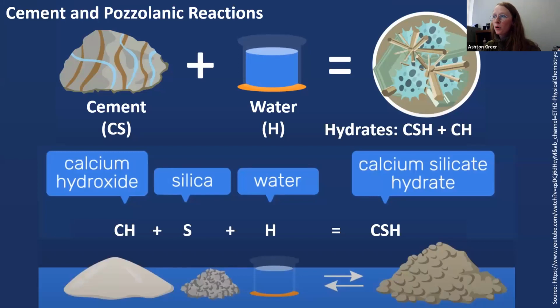So hydraulic cements like Portland cement become adhesive through a chemical reaction between the dry ingredients and water. Hydraulic cements are essentially made up of a mixture of silicates and oxides that react directly with water to form the hydrates calcium silicate hydrate and, secondarily, calcium hydroxide or lime. These compounds act as adhesives that bind other materials together and gain strength over time as they cure. Pozzolans like Mazama ash are siliceous materials that in the presence of Portland cement and water will basically react with the calcium hydroxide released by the cement hydration to form compounds possessing cementitious properties. So alone, they have little to no cementitious value at all, but in the presence of cement, they can create reactions that continue adding strength for even longer periods of time than cement alone.